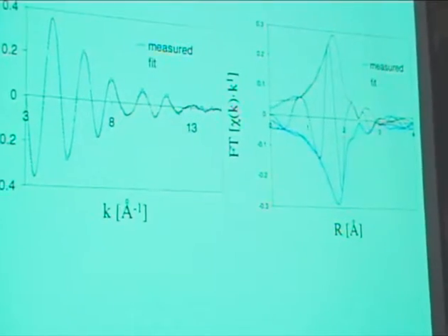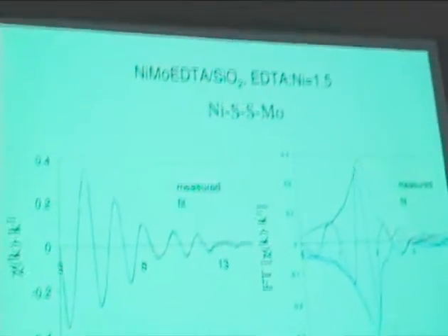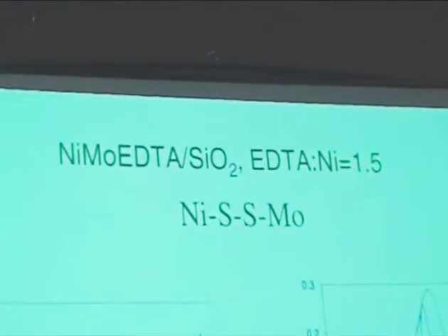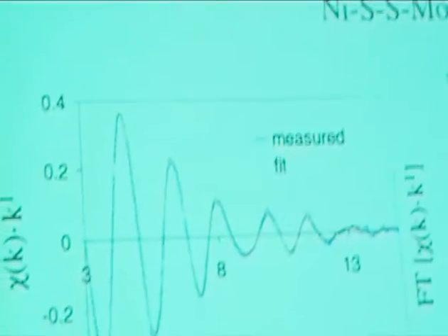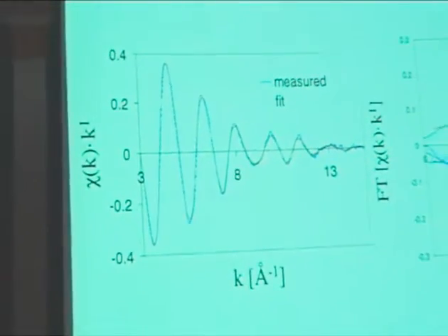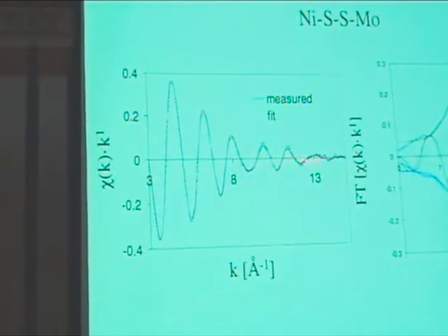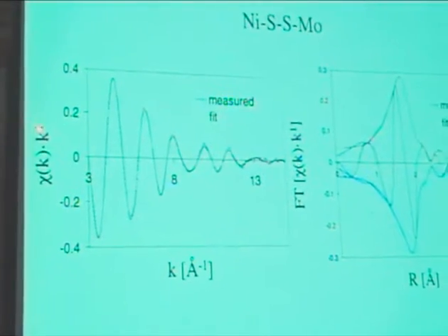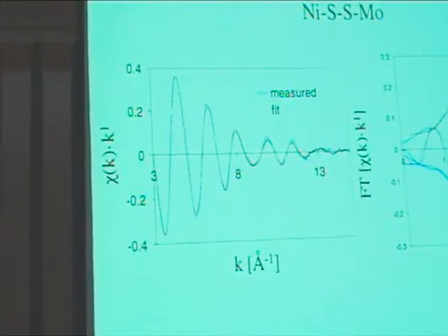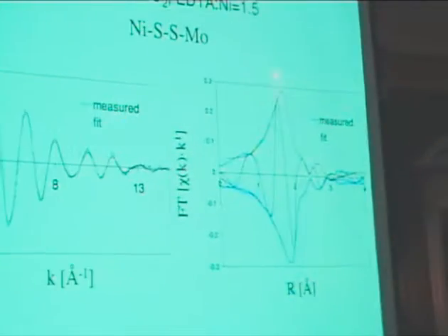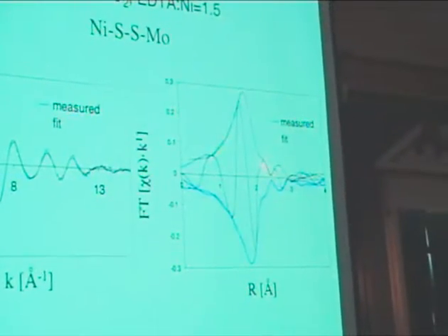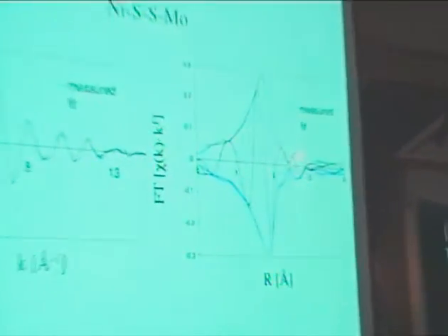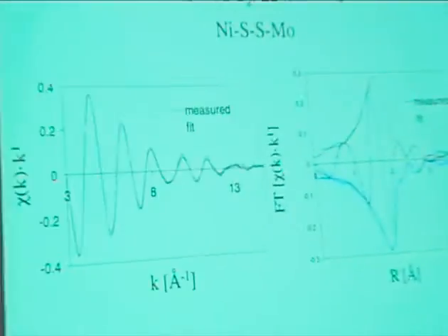And I'll show you. So let us zoom in on the nickel. So let us go to the 8,000 electron volt edge and look at the EXAFS spectrum there. And let's take the background off. So here is the EXAFS spectrum then. It's multiplied by k to the power 1. And we do a Fourier transform, and we see that we have one main peak, maybe a shoulder here, and maybe, well, definitely another peak here, and then it's most probably noise.